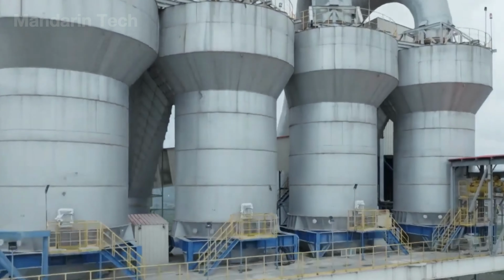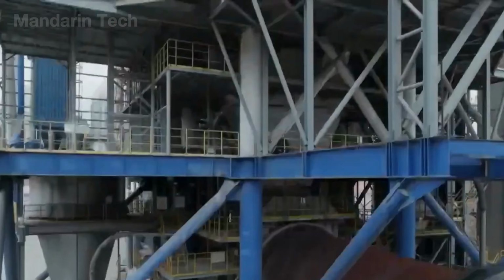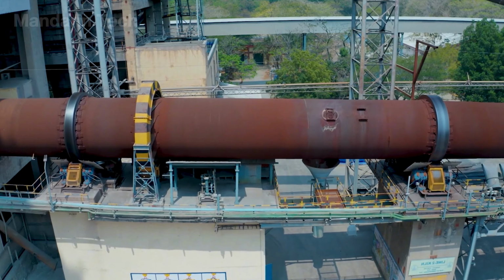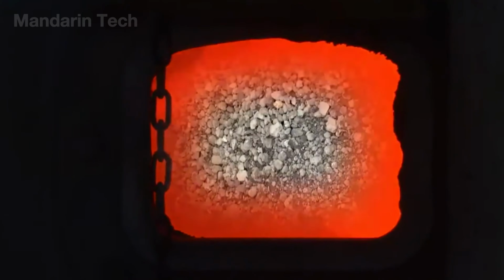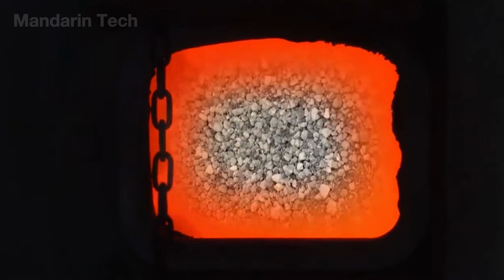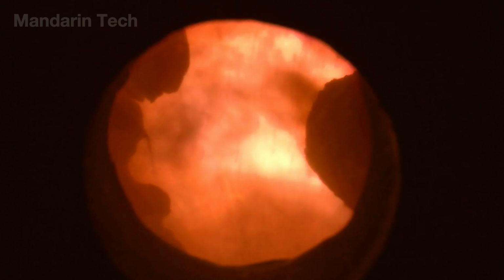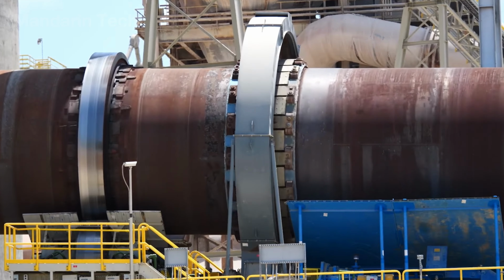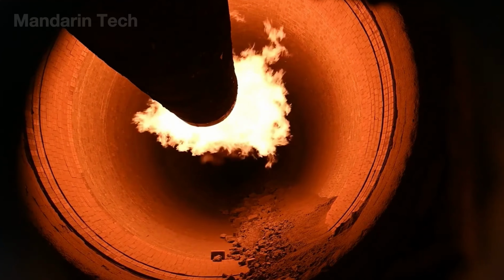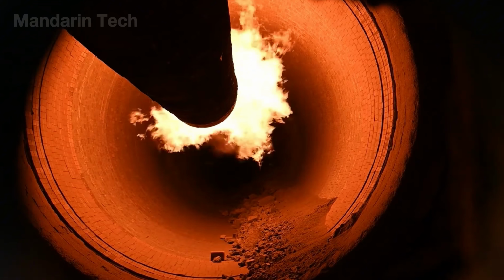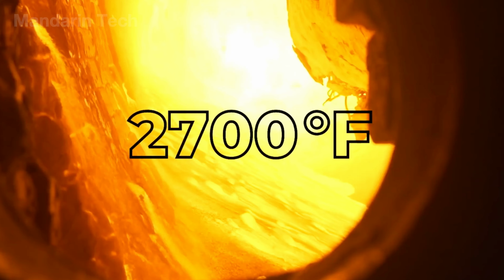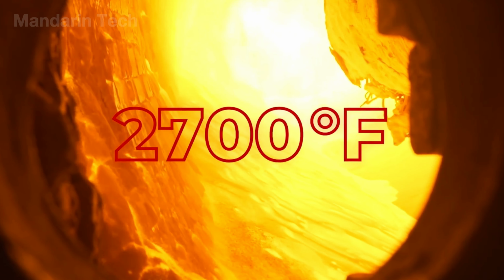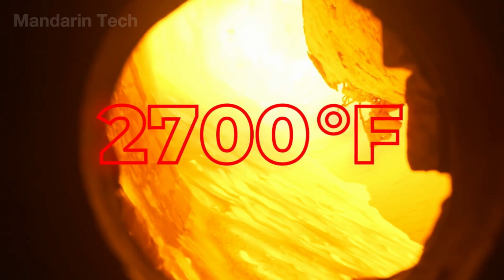The deep rumble of the rotary kiln mixes with the glow of the red-hot flame, creating a steady industrial rhythm. Inside the long steel tube, raw meal from the preheater drops in and slowly slides along the refractory lining, turning with the slight tilt of the kiln. As it moves into the hottest zone, each grain of limestone and clay is exposed to more than 1,180 degrees, where their original structure begins to break down and reorganize into new minerals.